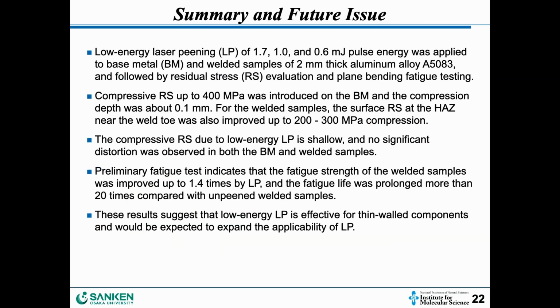So let me conclude my presentation with this view graph. As I explained, we confirmed the effect of low energy laser peening with energy of about 0.6 and 1.0 millijoule, one or two orders of magnitude smaller compared to the conventional laser peening system. However, we got a promising result: high compressive stress on the surface, preventing distortion of the material and increasing the fatigue strength.